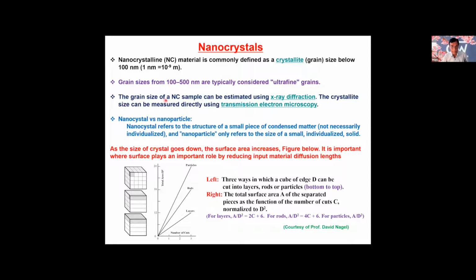Now, the grain size of nanocrystalline sample can be estimated by X-ray diffraction. The crystalline size can be measured directly using transmission electron microscopy. And if you compare those, nanocrystalline refers to the structure, a small piece of condensed matter, not necessarily individualized, and nanoparticles only refers to the size of a small individual solid. So sometimes people have a problem in differentiating nanocrystal and nanoparticles.